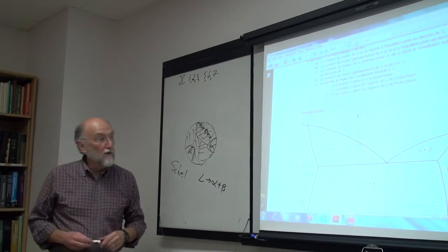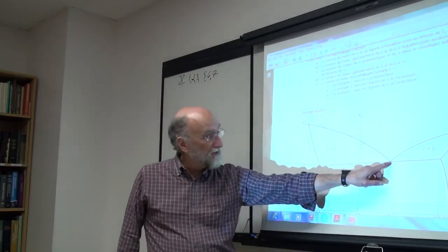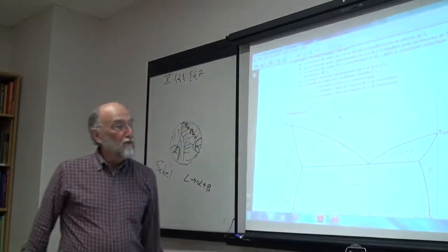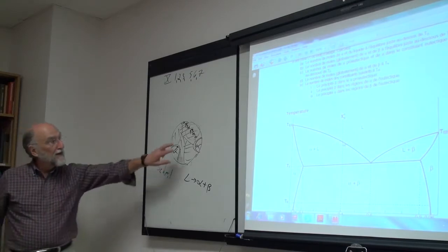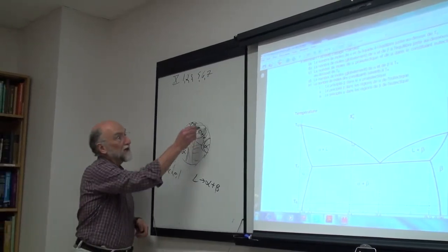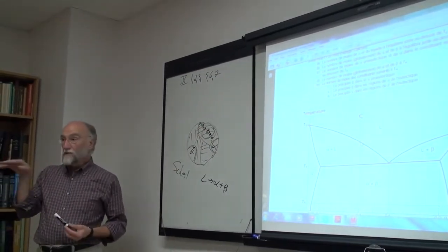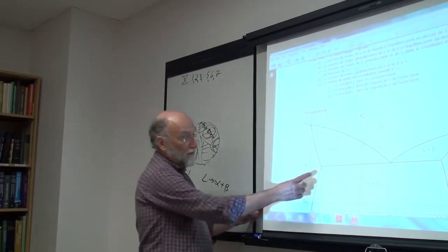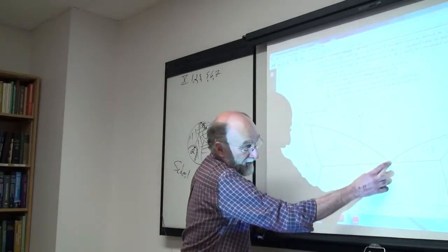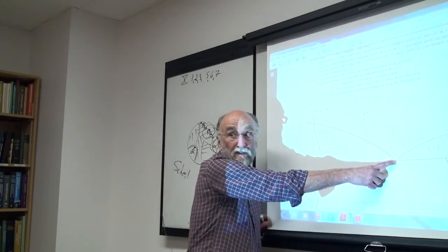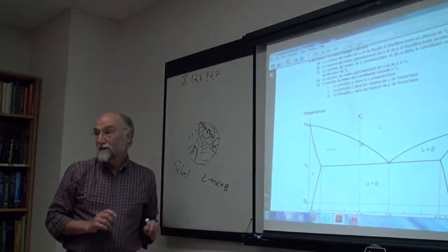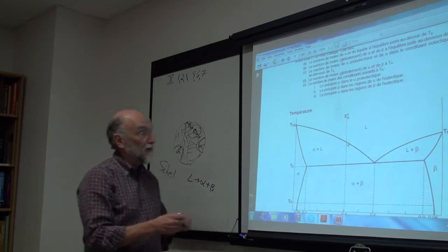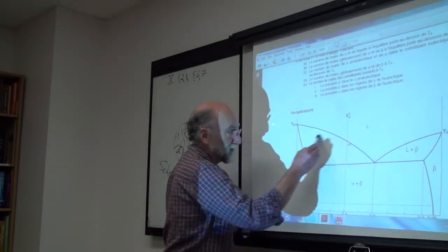Okay, so your overall eutectic is of this composition, and it consists of alpha and beta. If you want to find the ratio of alpha and beta within the eutectic grain, you take a eutectic grain and you want to find the ratio of alpha to beta within it. Then you apply your lever rule between this point and the overall composition of the eutectic. Okay? So the alpha in the eutectic divided by the beta in the eutectic would be this distance over